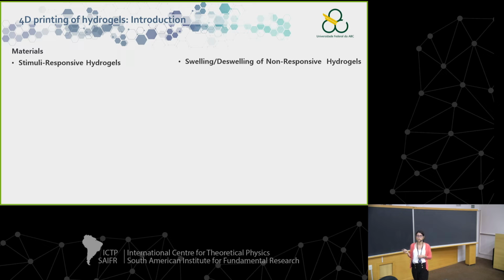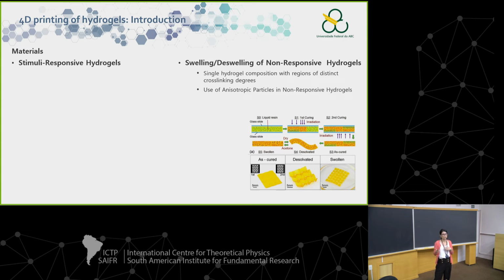In the case of non-responsive hydrogels, we can vary the cross-linking density. So in this work, between these two glass slides, we have ink that is photocurable. We apply a controlled light with a controlled intensity. We end up with different cross-linking degrees here, the same on the bottom. We take this hydrogel and we remove the unreacted parts, and then dry it and place it in different solvents, so we have this movement. So this is the printed hydrogel. When it is desolvated, we have this origami, and then it comes back to its original shape.